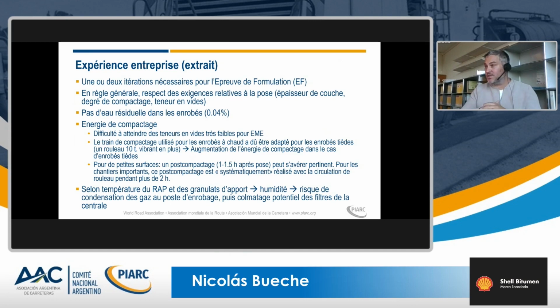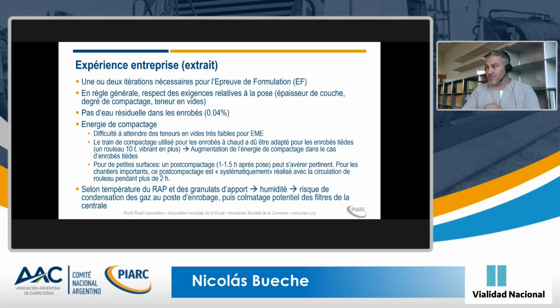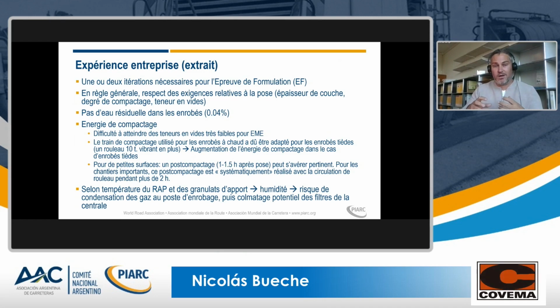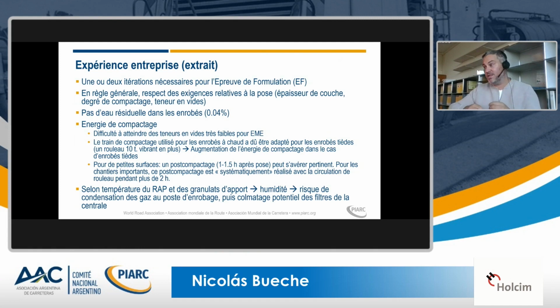The compaction was also interesting, and this has been measured also by the construction company. Basically, for the compaction energy, the company needed one more compaction vehicle to make sure we get a sufficient density and the needed void content. In the case of warm mix, we need a bit more energy in situ to ensure we have the right compaction degree.